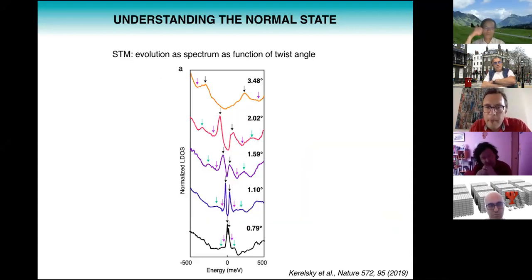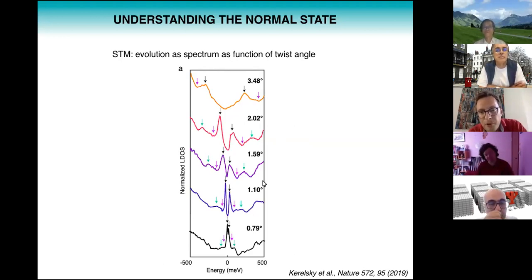So let's now try to compare this to our calculations. But before we do that, we can also look at the twist angle dependence of the tunneling spectrum. Here you see the result from the Columbia group for 5 different twist angles. And as you would expect, these Van Hove singularities keep approaching, but weirdly, they keep doing that. So based on the band structure picture, at some point beyond the magic angle, you would expect that they separate again, but this doesn't seem to happen in this experiment. So this is, I think, a mystery.